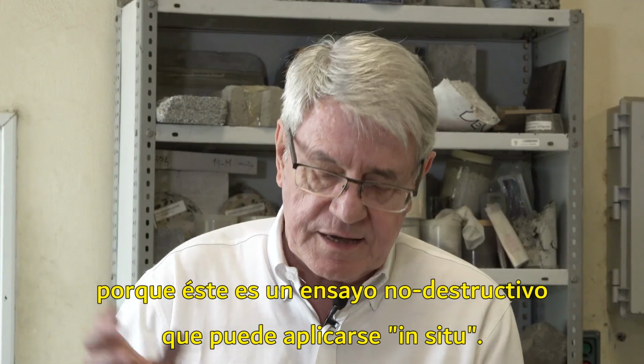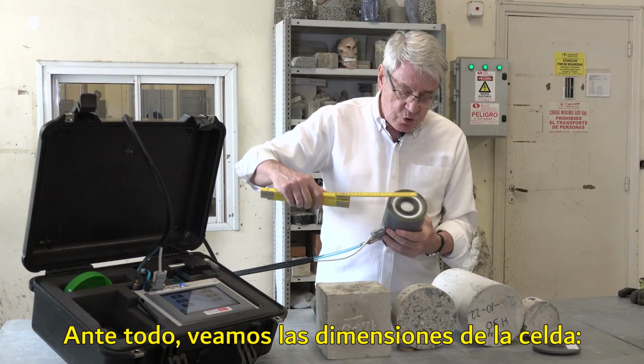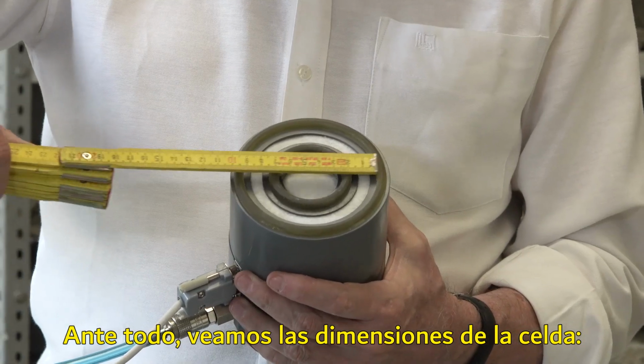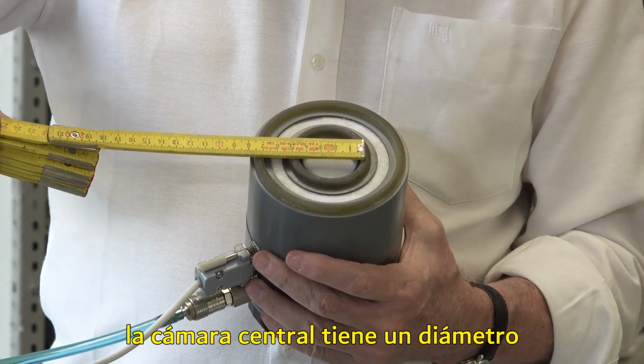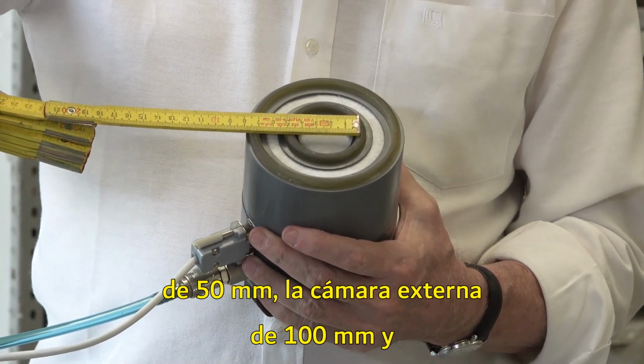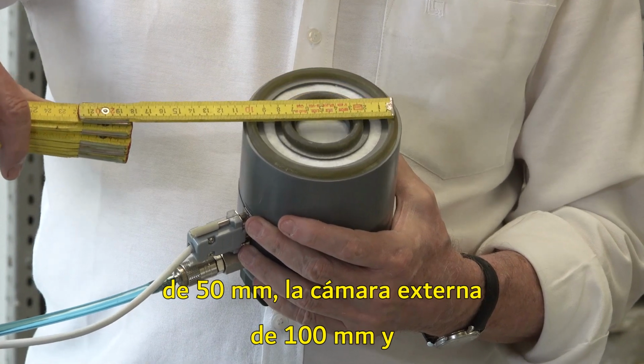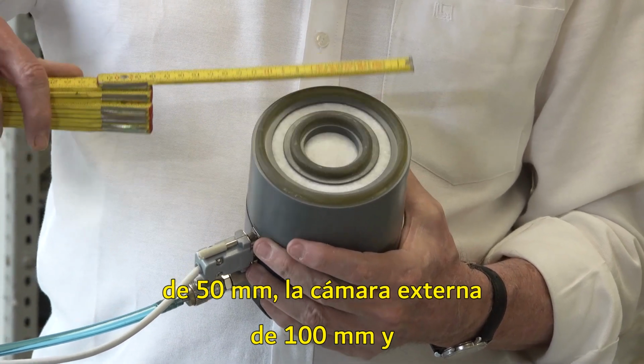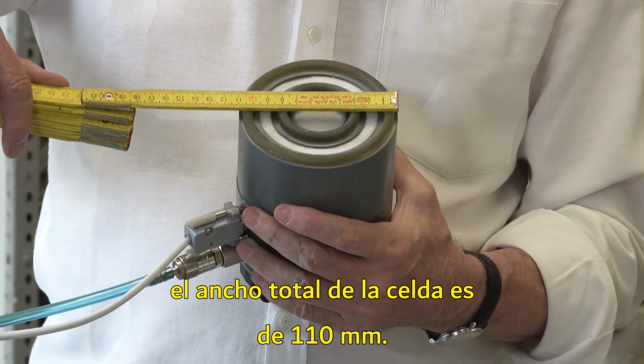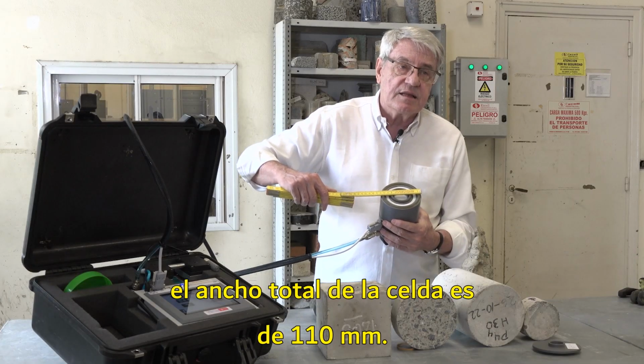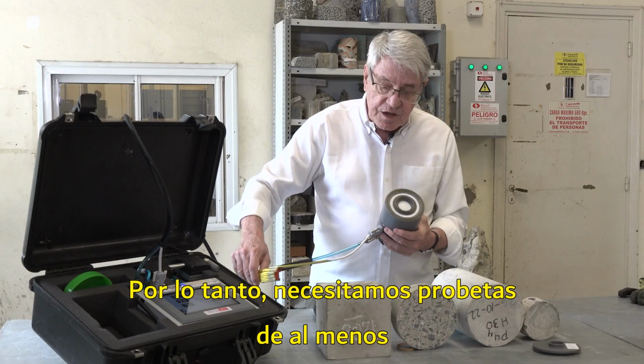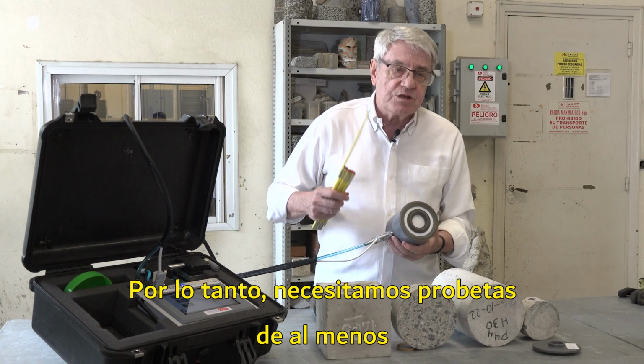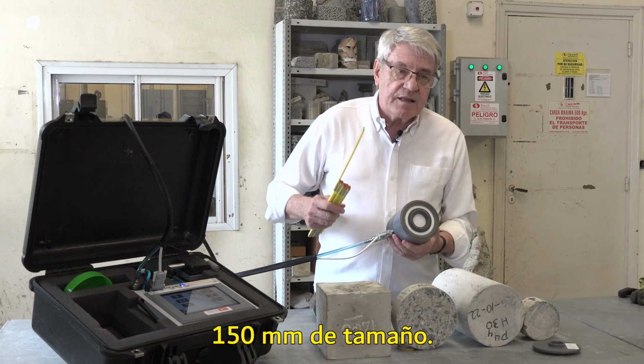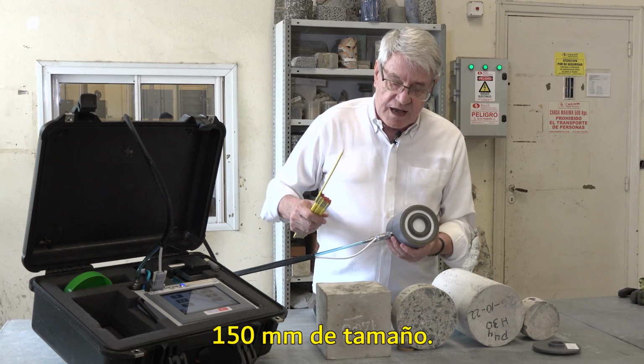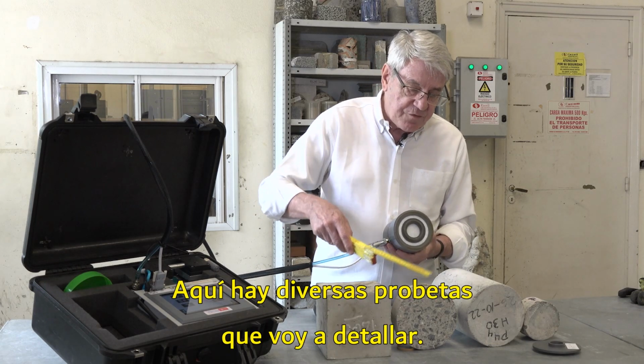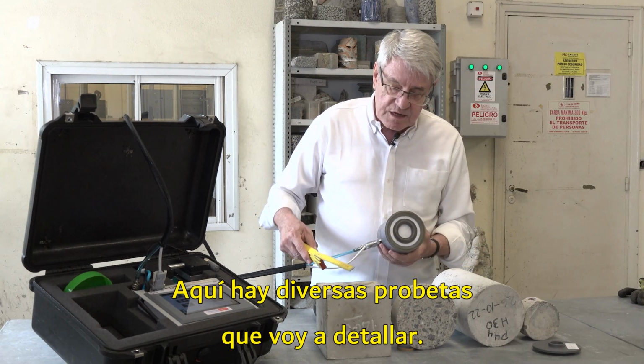First of all, let me show you that the dimensions of the cell are: the inner chamber has a diameter of 50 millimeters, the outer chamber of 100 millimeters, and the total width of the cell is 110 millimeters. Therefore, we need samples which have at least 150 millimeters of size. So here we have different samples that I will describe.